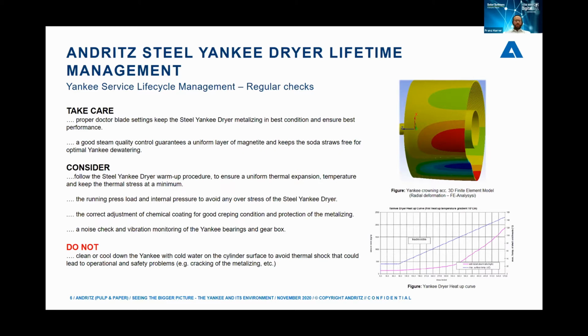It's important to follow the warm-up procedure when heating up the Yankee. This ensures a uniform thermal expansion and keeps the stresses on the Yankee at a minimum level. And as soon as the Yankee has achieved its operating temperature, we can load the press and dry the paper on the Yankee without any danger. It's for sure mandatory to keep the press load and the Yankee pressure in the allowed range to keep the fatigue lifetime of the Yankee dryer.